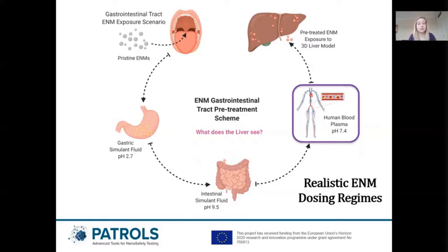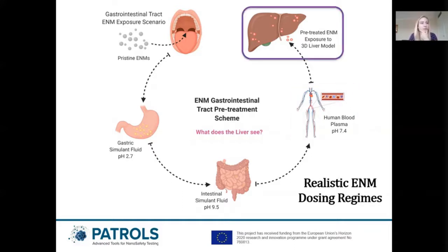Following this, we then decided to add an additional incubation of 1 hour in human blood plasma prior to further dilution in media and exposure to the 3D liver cells. So this particular SOP or scenario mimics the gastrointestinal tract ingestion exposure scenario to the liver.